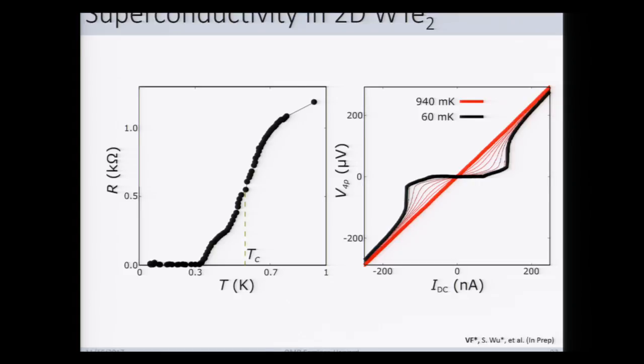We can then do this sort of basic characterization. So we have the 4-terminal voltage as a function of DC current bias. And we see, again, no voltage drop at low temperatures up to some value. And we see a very sharp onset voltage rise at a particular current that we'll call the critical current. As we increase the temperature, we see a smooth transition from this highly nonlinear behavior to typical ohmic behavior of